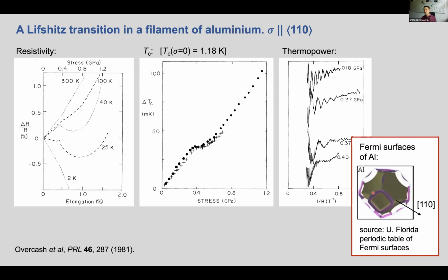So what's going on is shown here. These are the Fermi surfaces of aluminum, and the stress direction, the direction along which they're applying stress, is the 110 direction here. And the key thing that's going on is these necks here and here. Those necks are becoming narrower and eventually break, and that's the Lifshitz transition that drives these little anomalies.